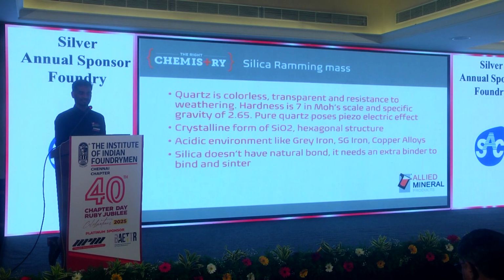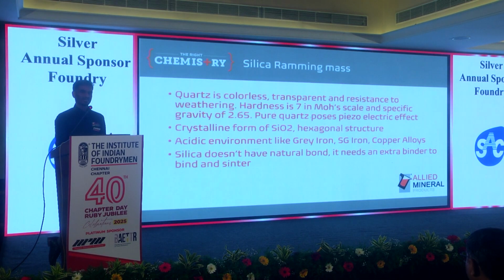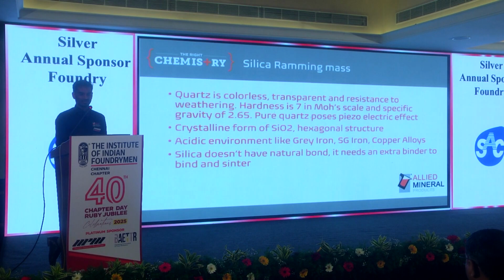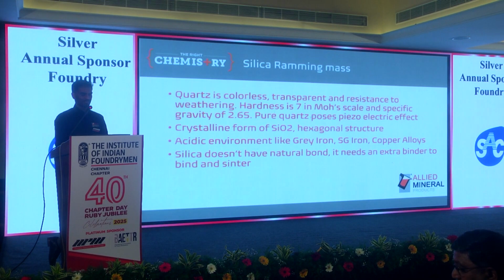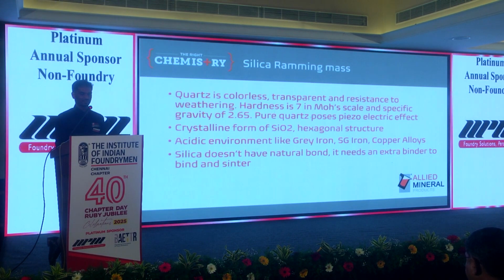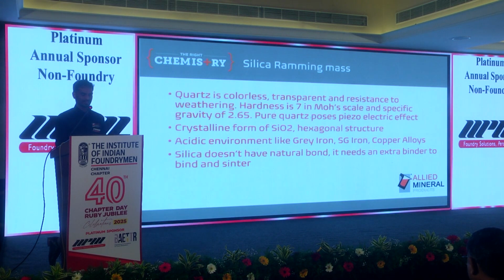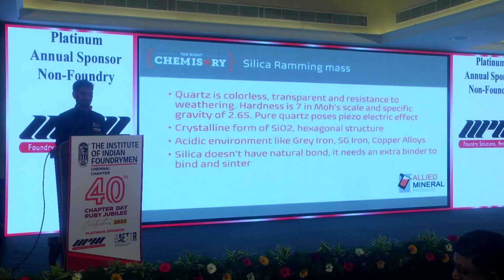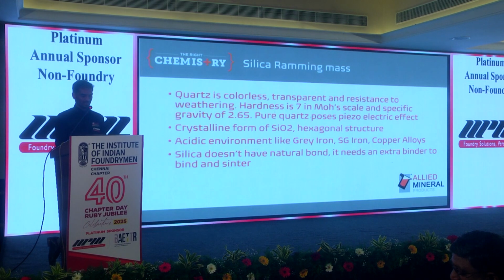Quartz is colorless and transparent, and the hardness is almost 7 on the Mohs scale, and the specific gravity is 2.65. It has a good piezoelectric effect. The crystalline form of silica is what we typically use, and it is hexagonal in structure. Typically it's acidic, as I said earlier. That's the reason we use it for grey iron, SG iron and copper alloys, where the slag tendency is also almost acidic in nature.